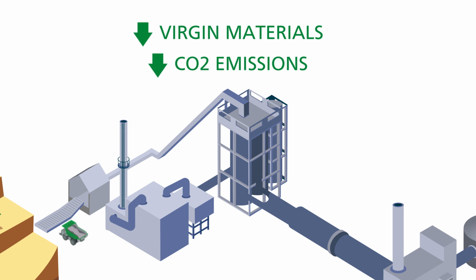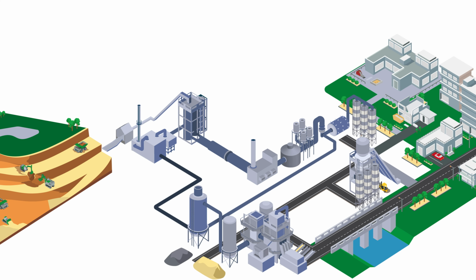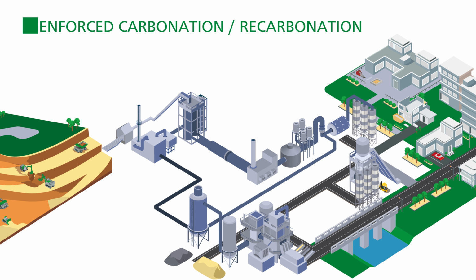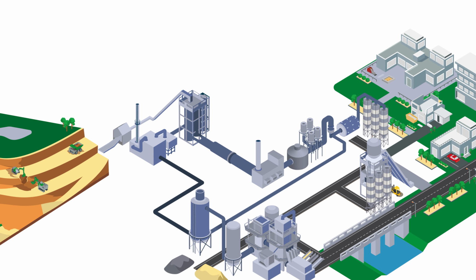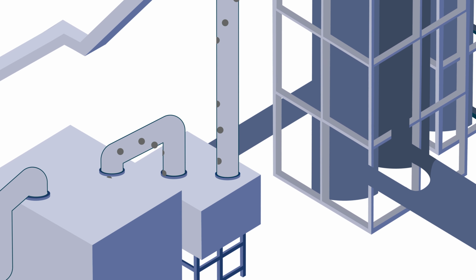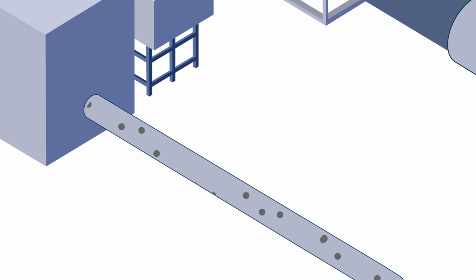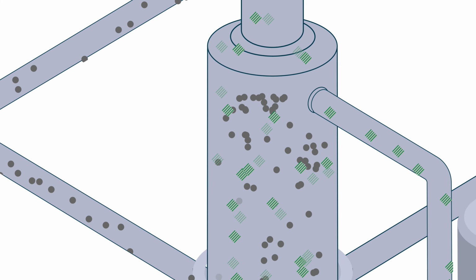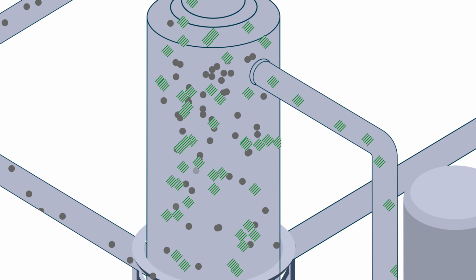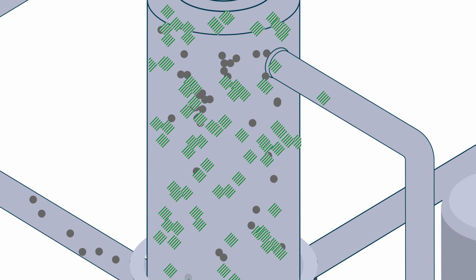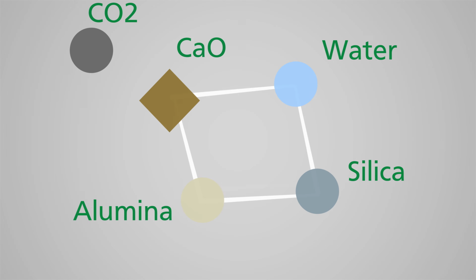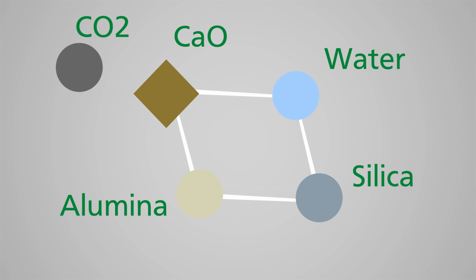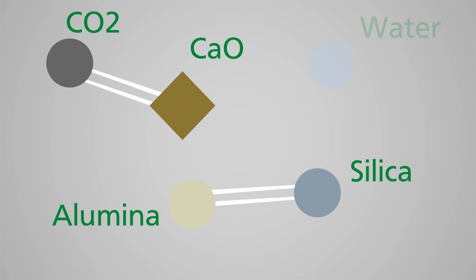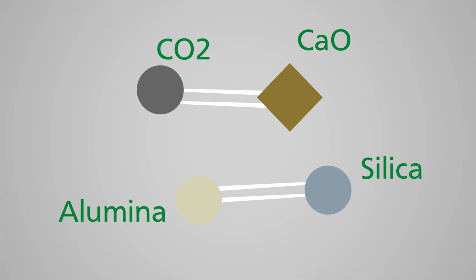On the other hand, the recycled concrete paste, due to its remaining carbonation potential, can be used for a CO2 sequestration technology called enforced carbonation. The carbon dioxide, which is released by the clinker production process, is redirected and cooled down. In the absorber, the RCP gets continuously exposed to the flue gas stream. The CO2 reacts with the calcium oxide present in the RCP and forms calcite, the main mineral found in limestone.